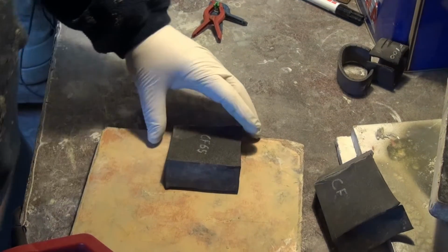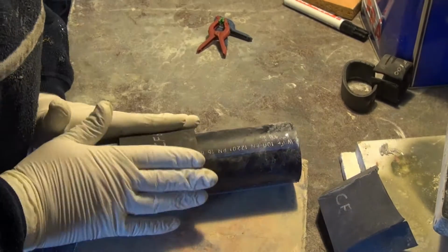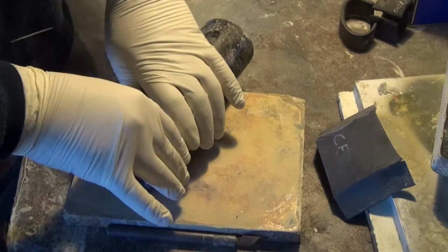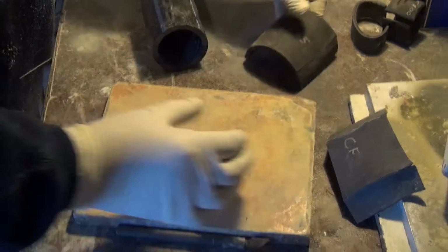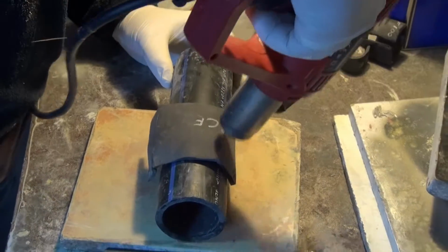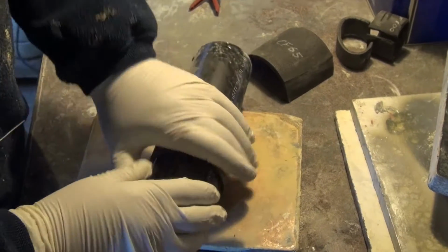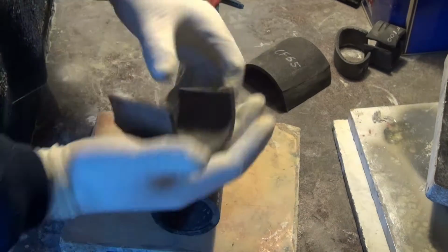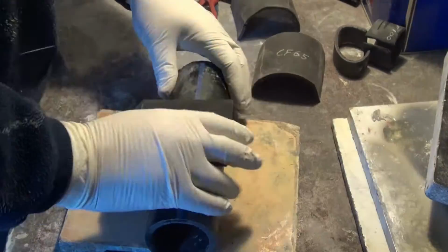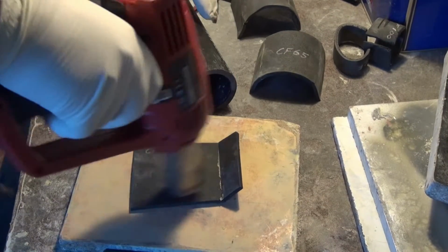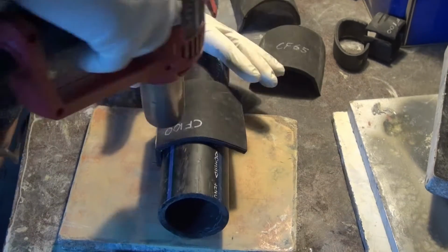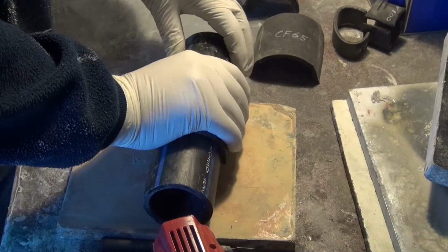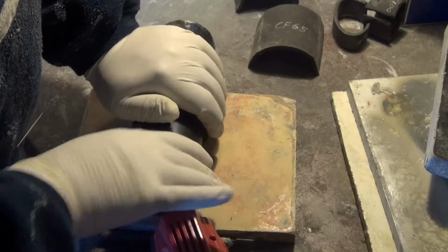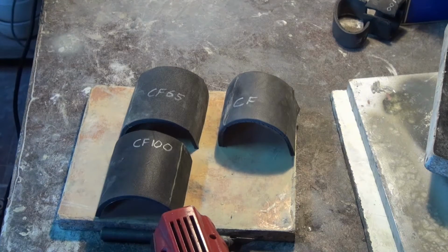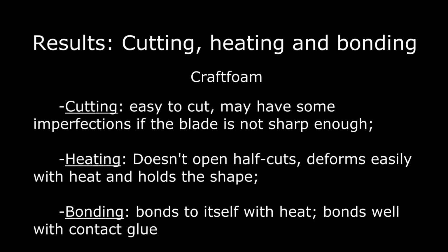Heat was then applied to the three samples to obtain a cylindrical shape in order to verify the stability of the form. To get the cylindrical shape, the CF100 sample needs to be heated on both sides, unlike the craft foam and the CF65 samples. All polyprops foam samples keep their shape after they are cooled.